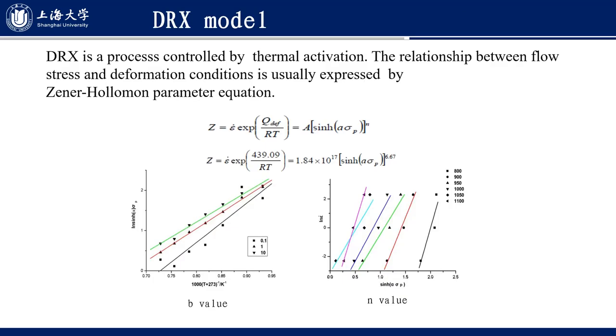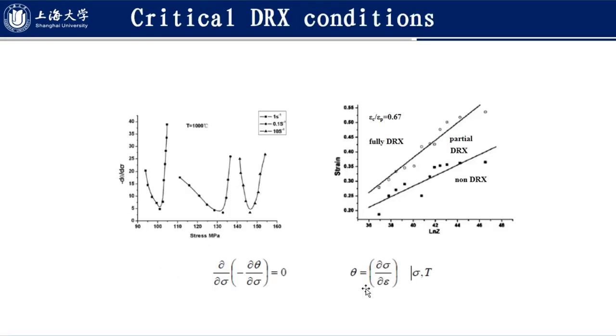Dynamic recrystallization is a process controlled by thermal activation. The relationship between flow stress and deformation conditions is usually expressed by the Zener-Hollomon parameter equation as follows. The critical dynamic recrystallization conditions are obtained according to the following equations. And the fully dynamic recrystallization area, non-dynamic recrystallization area, and partial dynamic recrystallization area are obtained.